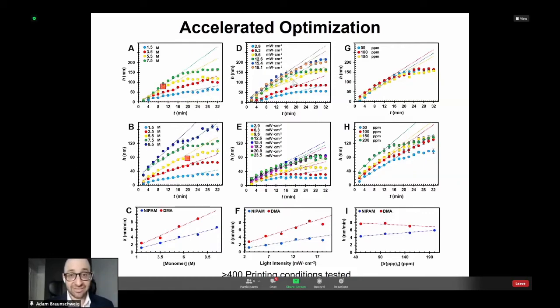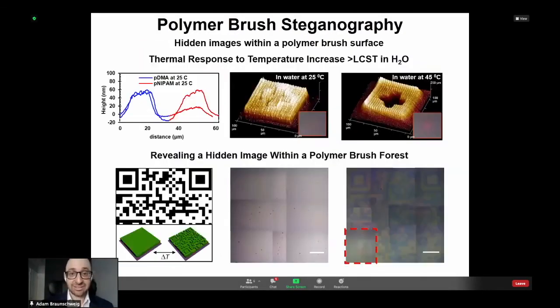where for both DMA on the left and NIPAM on the right, he explored the role of monomer concentration. He explored the role of light intensity, monomer concentration, and the concentration of the initiator here. And then he was able to determine how each of these different parameters affected the growth rate. So here, what he did is, out of these 400 different conditions he explored, he chose one condition for NIPAM, one condition for DMA, where under these conditions you could grow polymers of the exact same height. Right, so here you see the first hidden image.